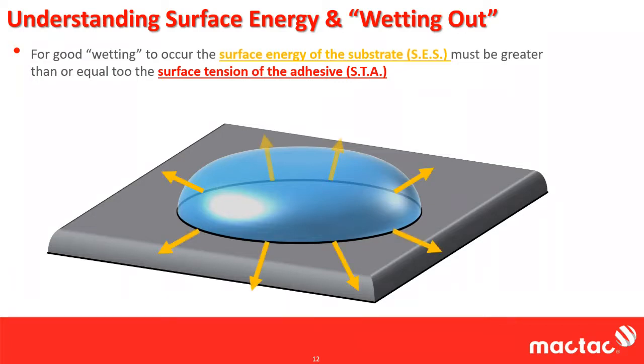So now all those molecules that were on the surface, again, remember they had no one to play with above them because they were at the very edge. They have molecules beneath them, but there was nothing above. Well, now they have something to interact with, and what they're interacting with is the adhesive. So again, the surface energy of the substrate, all that extra surface energy, is now pulling the adhesive that's in contact with the surface, trying to stretch it out. In exact opposition to this, we have the surface tension of the liquid,